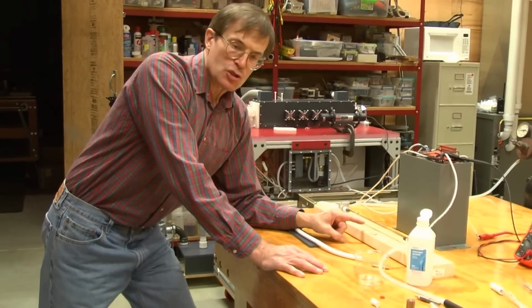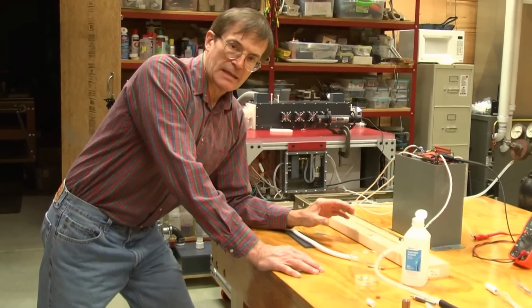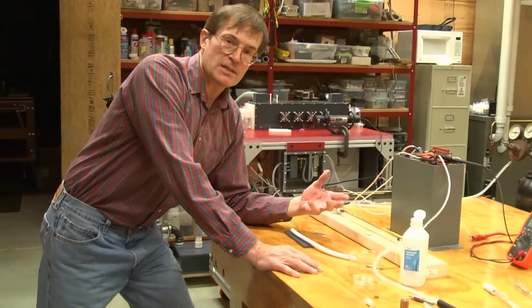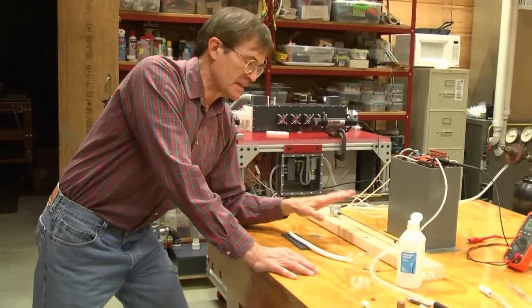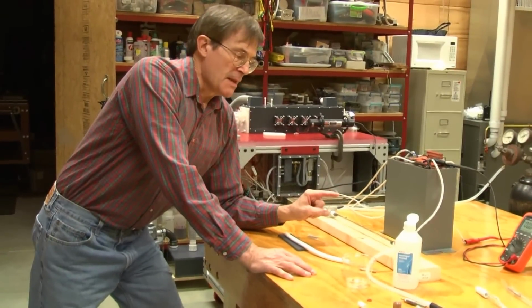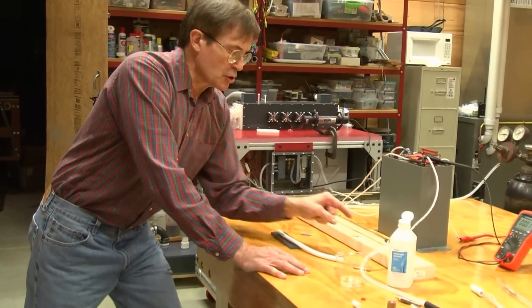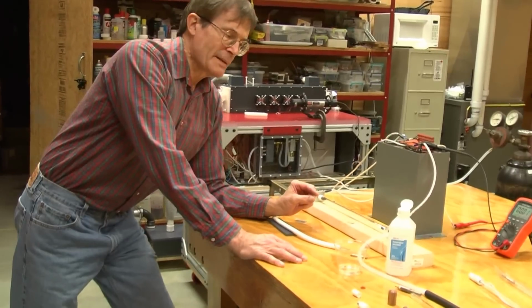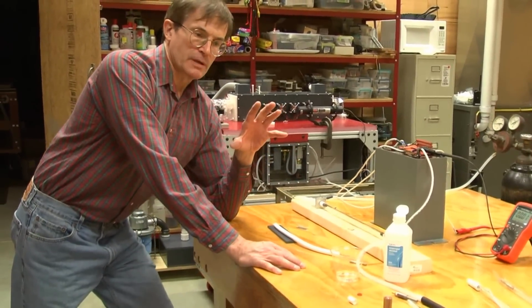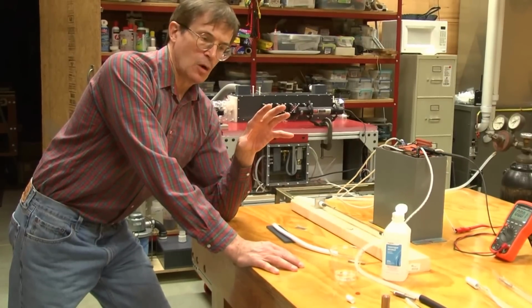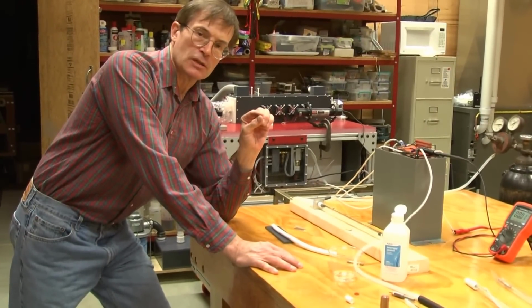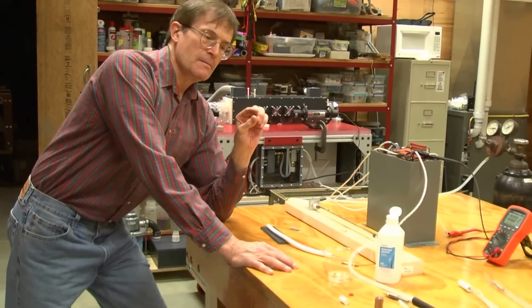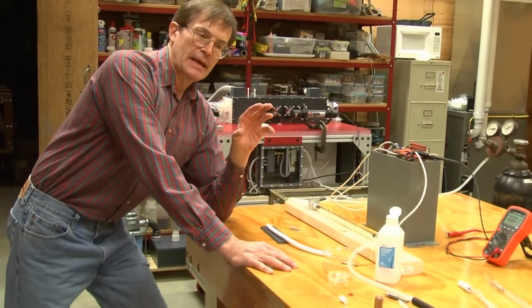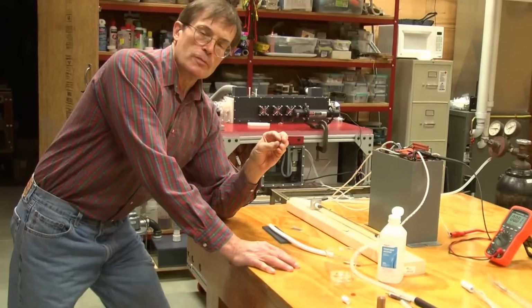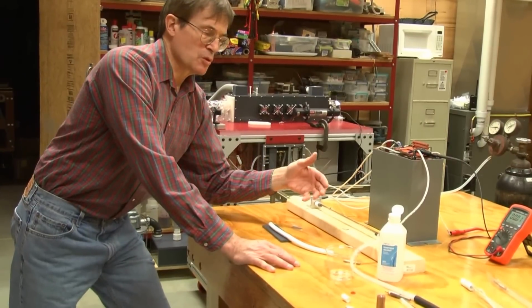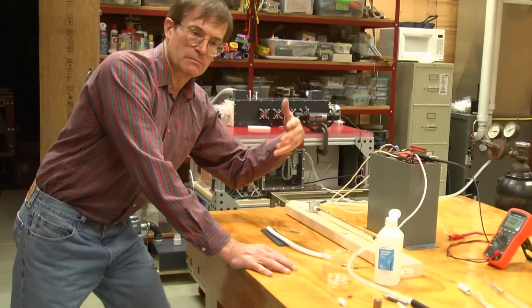When you take one of these tubes and you put the same amount of energy through it and it discharges 3 or 4 times faster, it's much quieter, despite the fact that it's a more violent operation. Because the pressure within the tube is so low, what I believe is happening, and this hasn't been really reported in the literature, even though there's a lot of description of ablating wall lamps, is that the silica and the oxygen that are ablated from the wall do not distribute evenly within the tube and produce what's sort of a temporary silica-oxygen flash lamp.